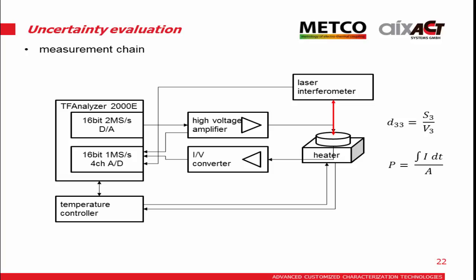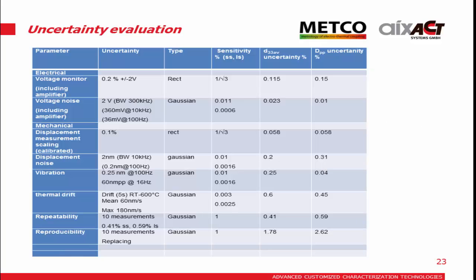Uncertainty evaluation was also a part of the project, and in this case it sounds rather simple because we just measure the displacement and voltage, and additionally the charge, but there's still a lot of influences that have to be taken into account, like especially vibration influences and changes in airflow or thermal drifts, and all of this was evaluated for a certain range of measurement parameters, so that the goal to be more precise than, or in the range of 1%, could be achieved, but the reproducibility is still around 2%, and this is still focusing on more precise handling of the samples. But still it should be easy to maintain and operate.